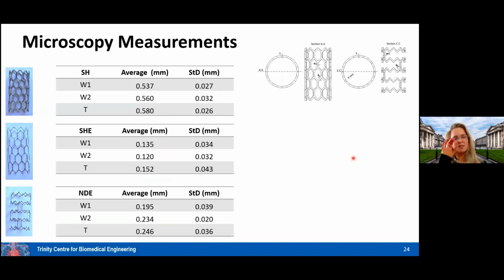I just want you to appreciate these because later this has implications for the radial stiffness of these stents when we test them. You can see we've gone from about 0.5 millimeter, so 500 microns, in the as-print stents, which are quite easy to print because they're nice and thick, but they have a lot of dross around them, a lot of particle attachment or defects. Once etched, I'll show you the surface finish in a moment, but we can get down much closer to typical commercial stent design, so down to around 120 to 150 microns.